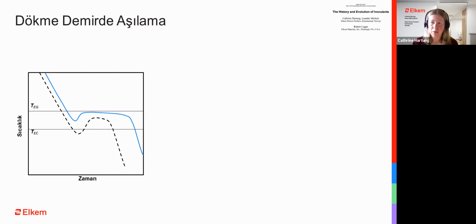One key parameter often looked at, and which we have learned from the slides on solidification and nucleation is important, is the undercooling needed before solidification starts. This undercooling can be seen in the cooling curve as the temperature difference between the low eutectic temperature and the TEG line. And this is the low point that you see before it increases again and flattens out.